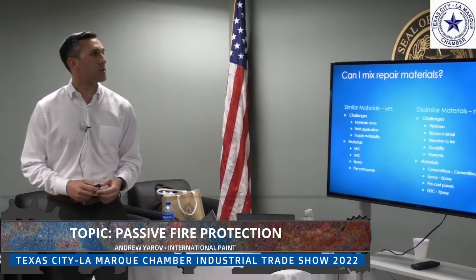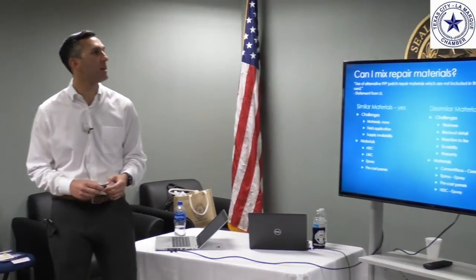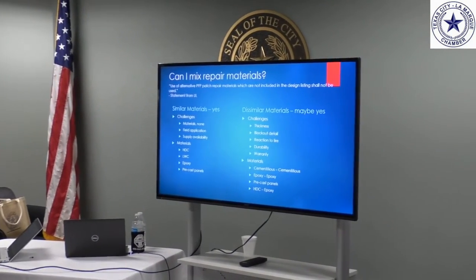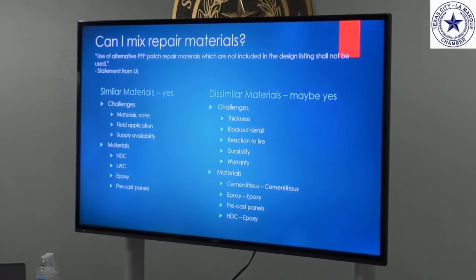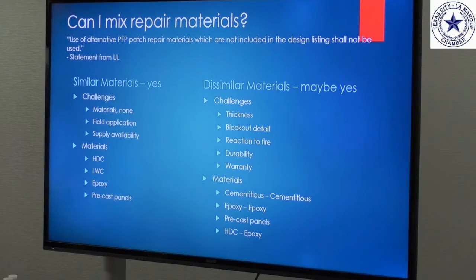So let's talk about solutions. Can I mix repair materials? Let's see what UL has to say about it. So per UL, the use of alternative PFP patch repair materials, which are not included in the design listing, shall not be used. So basically what that says is you have to use like for like material. If you have cementitious material in your facility and you need to effect a repair, unless you choose to fully strip off all that lightweight cementitious, you will have to go back and repair with the same material. That's just per the UL standard. That's how you have to follow the rules for that specific product.